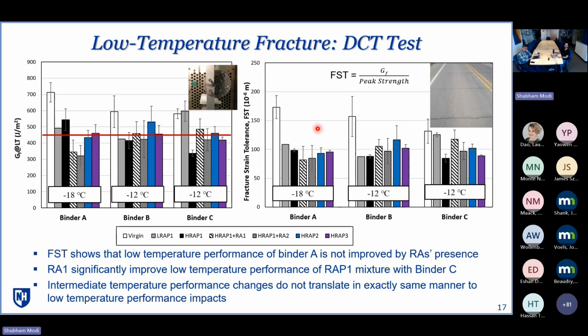But here, as we can see in the second graph, FST shows the parameter that is normalized, fracture energy normalized with the peak strength, and we can see that statistically the RA had no impact on the results, and RA1 is showing better improvement in the case of binder C. However, the trends on the low temperature side are not as consistent as we observed in the intermediate temperature properties.